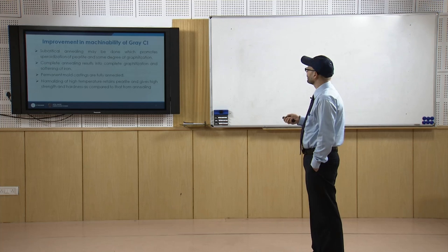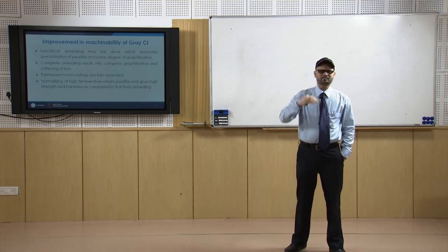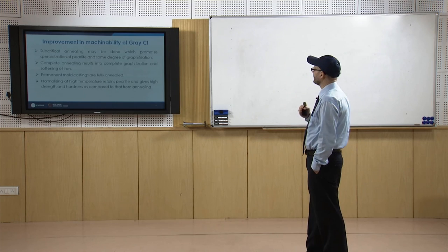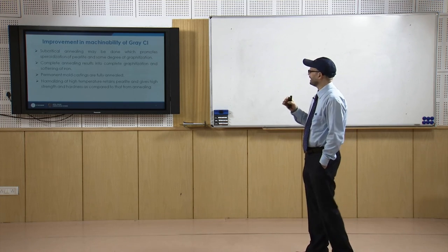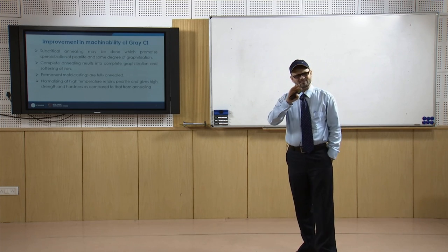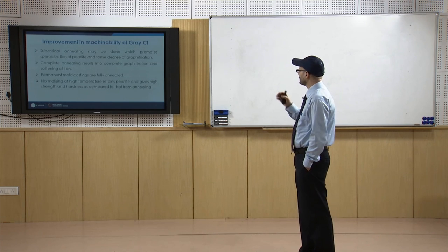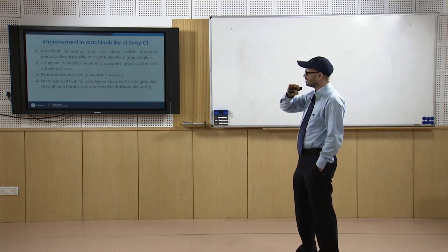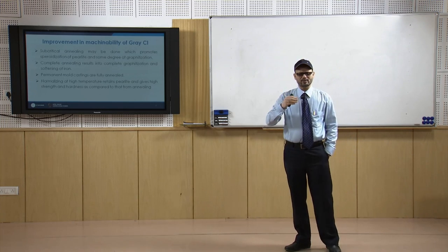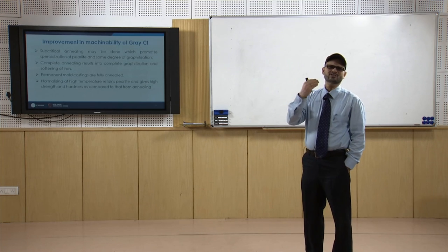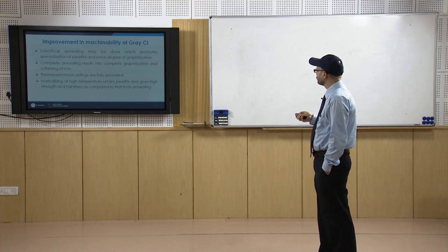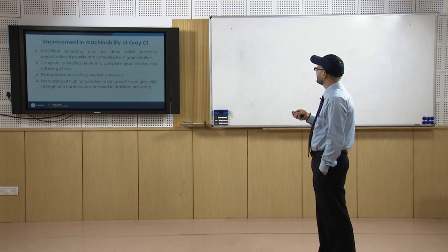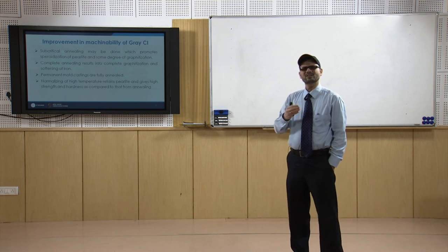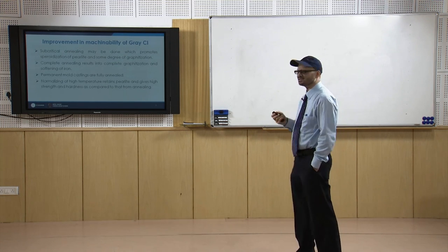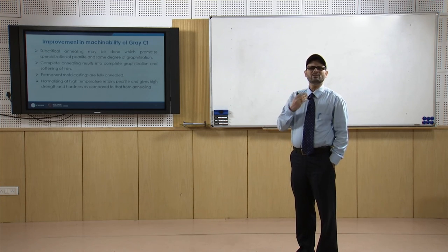Then, we can also do complete annealing. For complete annealing, we go above the critical temperature, around 900 to 950 degrees centigrade, and then cool in the furnace at a very slow rate. So, we go into the austenitic range and then cool very slowly. Certainly, in grey cast iron in the presence of graphitizers like silicon, under that slow cooling complete graphitization will take place, and that will make the iron very soft. It will result in a softened structure, and it will improve the machinability.